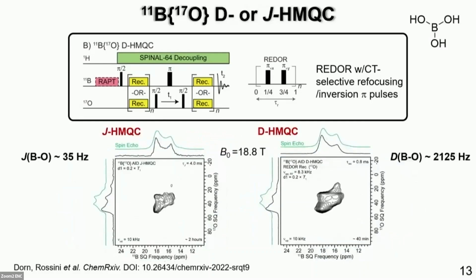Now, we could perform these HMQC experiments utilizing the scalar coupling, like Massiot and Gan showed. However, this requires significantly longer acquisition times because the boron T2 is so short, and the scalar coupling is about 2 orders of magnitude smaller than the dipolar coupling.